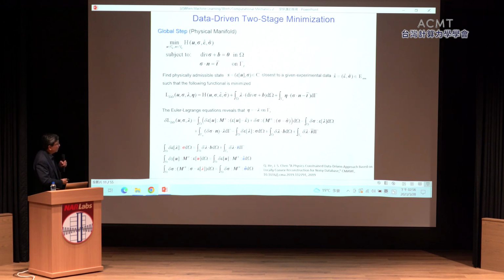The second equation allows you to relate experimental strain, epsilon hat, to the physical strain in terms of displacement. The third equation allows you to relate the experimental stress data to the physical stress state through Lagrange multiplier. So computationally, what you can do here is you start with some experimental strain state, and then from there you solve for the displacement field.